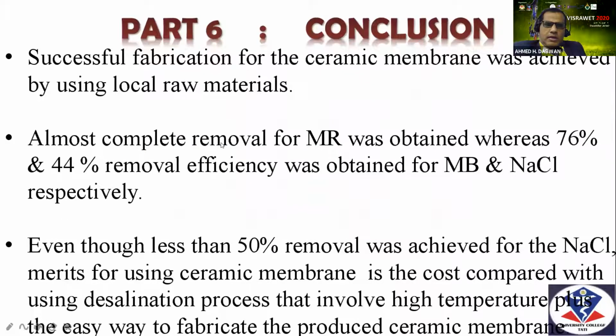And here the conclusion, I think successful fabrication of the ceramic membrane was achieved. We got almost complete removal for methylene red, 76% for methylene blue, and 44% for sodium chloride. Okay, that is, I think, a good achievement, because you can make series treatment, so you can get less and less sodium chloride.